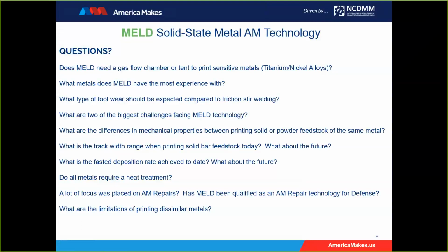And the first question is, does MELD need a gas flow chamber or tent to print titanium and nickel alloys? Good point. Yeah, I didn't mention that when I showed the titanium work with ATI. Part of that project is we were determining whether we needed a tent or we could do an open atmosphere. And so we printed the titanium, open atmosphere, no tent, obviously no gas flow chamber. And ATI measured the build plate and measured the print, and they only found minor differences in the nitrogen and oxygen content, indicating that we can print titanium, nickel alloys, and other sensitive materials without the need for a tent. Obviously, that means without the need for a gas flow chamber. And so we can now claim that MELD technology can expand its gantry-based platform to support these applications or these materials without the need for a tent.